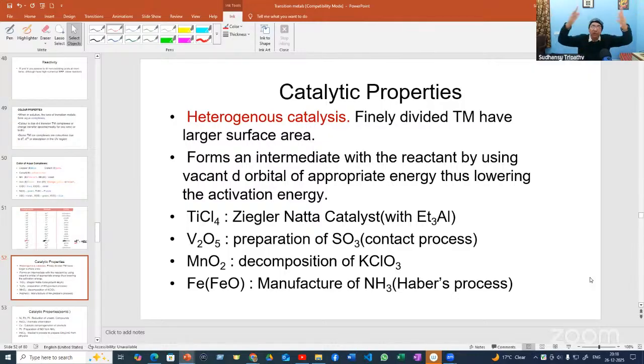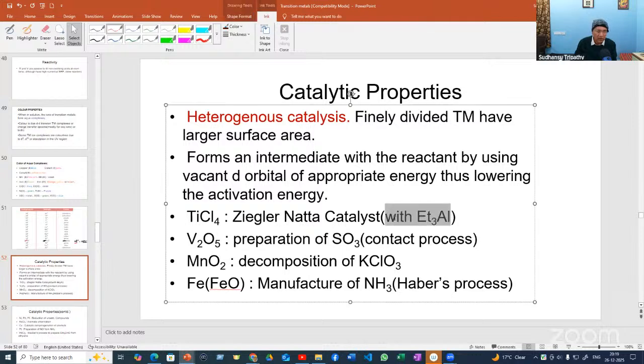Adsorption, the opposite is desorption. They are dissolved and they go as AB. So during this process, the activation energy is lowered. There are many catalysts like titanium tetrachloride, Ziegler-Natta catalyst for polymerization, stereoregular polymerization. This is used along with organometallic compound, triethyl aluminum. Vanadium pentoxide, preparation of SO3, the contact process. Manganese dioxide, decomposition of KClO3 to give KCl and oxygen. Iron nowadays used as a catalyst in manufacture of ammonia in Haber's process.